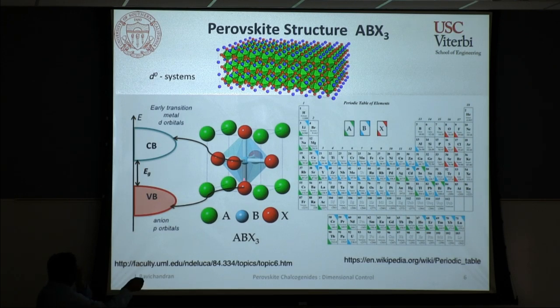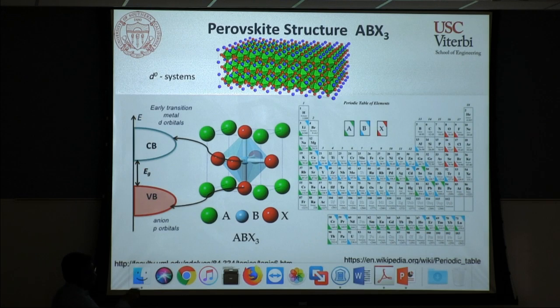Okay, typically the band structure of this system, if we were to talk about a scenario where we are taking these early transition metal elements that are shown here, is that your conduction band is made of the orbital nature of the B site element, and your valence band is made of the orbital nature of the X site element. Now, one of the interesting things that will jump out if you look at this periodic table is that the candidates for these A, B, X elements are all over the periodic table. So essentially, you can pick most of the elements from the periodic table, and you can build a material that